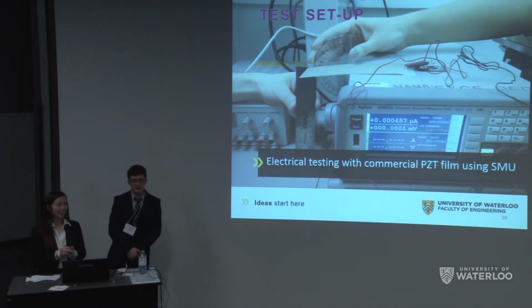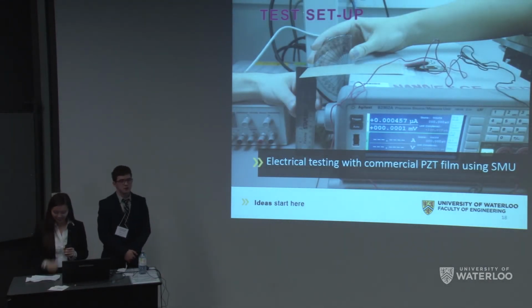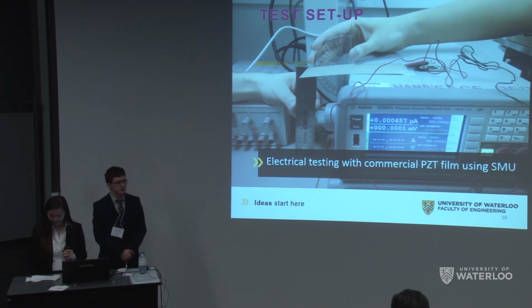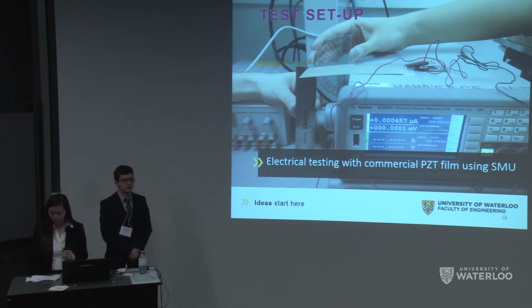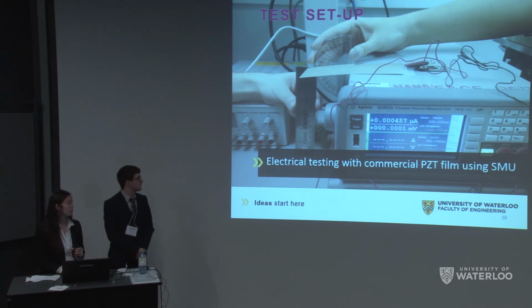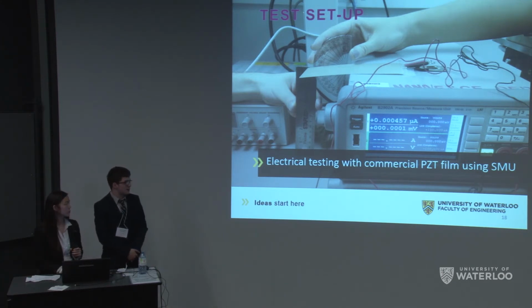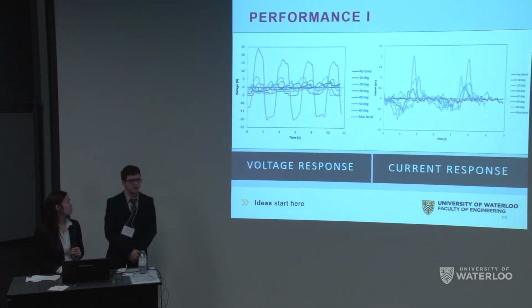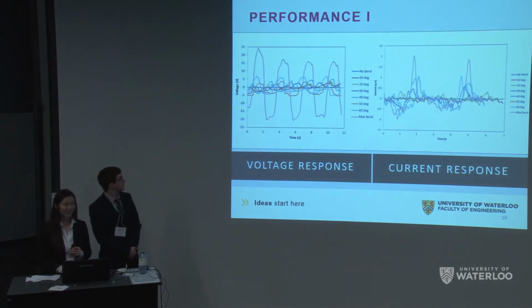So let's look at the test setup that we used. In order to normalize our displacement, we utilized the bend angle. As you can see in this figure, we used a protractor to ensure the bend angle was consistent across tests. We chose to look at a bend angle from 0 to 60 degrees, as that matched the typical motion of the knee during walking. We also looked at the max bending, which would be analogous to having more intense physical activity and larger movements. Based on this, we did current and voltage measurements using a precision source measurement unit.